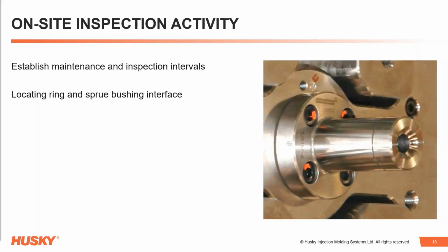Machine interface conditions should be reviewed. So make sure the locating ring is still in good shape with no nicks, burrs, or gouges. The sprue bushing should also be checked to confirm no leaks or gouges at the machine nozzle's spherical radius.